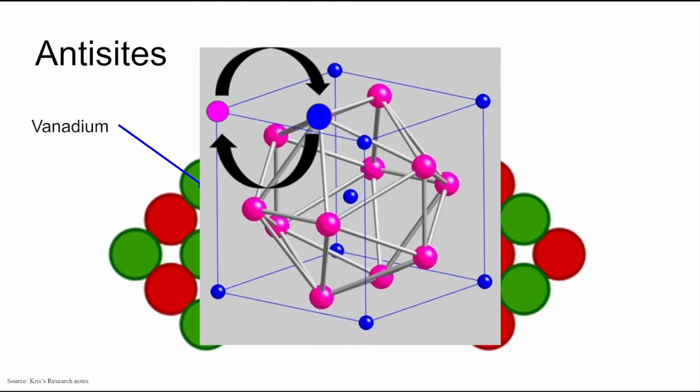The single phase of V3Si permits antisites with excess vanadium, a minimum of 75% vanadium and up to 81%, without phase segregation, remaining in a single crystal phase.